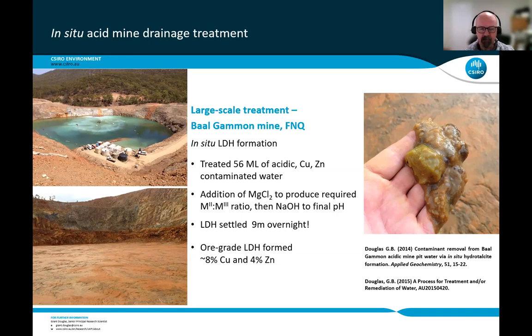And with that spontaneous formation, it immediately began to self-aggregate and settle. And from a pit that we couldn't see the bottom of, overnight all the layered double hydroxides had settled without the aid of flocculant or anything else. They had settled the 9 meters, and we could actually go out to the center of the pit and see the bottom. So then if you look at the right-hand image there, that's the actual layered double hydroxide. You can see it forms pretty much an amorphous-like gel structure. And then if you go to the bottom left slide there, you can see what it looks like on the bottom of the pit.